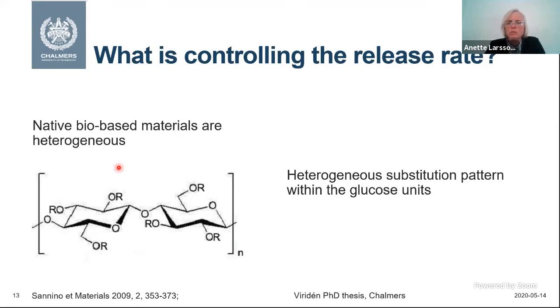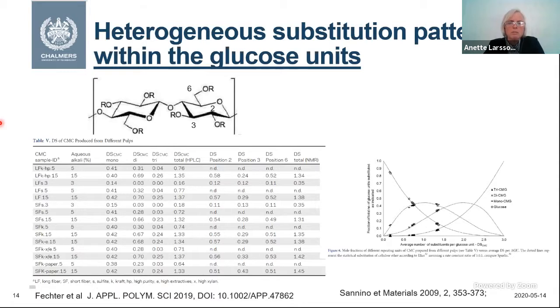And of course, we did know that the substitution pattern for this type of heterogeneous materials is very critical. And there are different types of substitution patterns you can talk about. It can be within a glucose unit. So here you have the 3 possibilities where the R group can be changed to an H, and then it's unsubstituted, or it can be a methyl group as it is one type in the HPMC. And they can be on this number 2, 3, or 6 position. And we will always have some kind of heterogeneity when it comes to where in the glucose unit it is substituted.